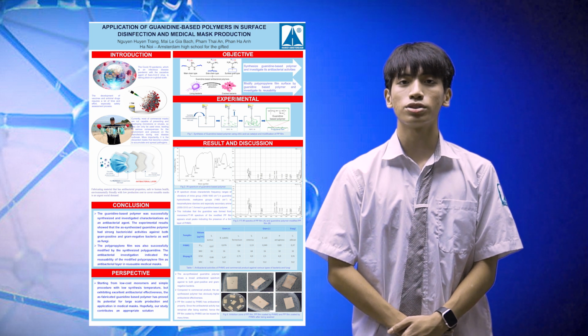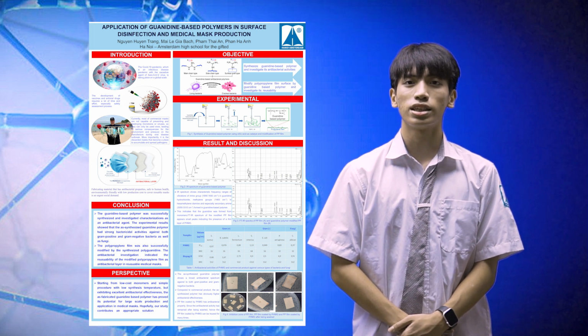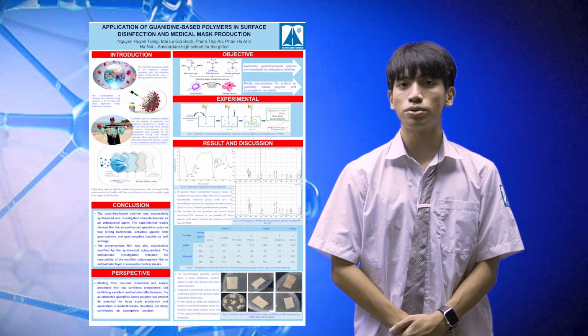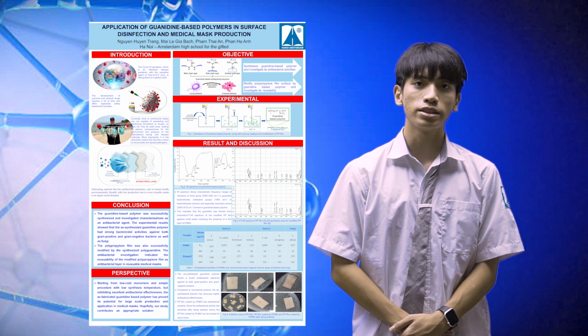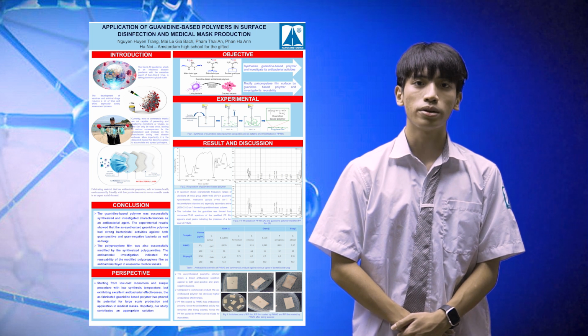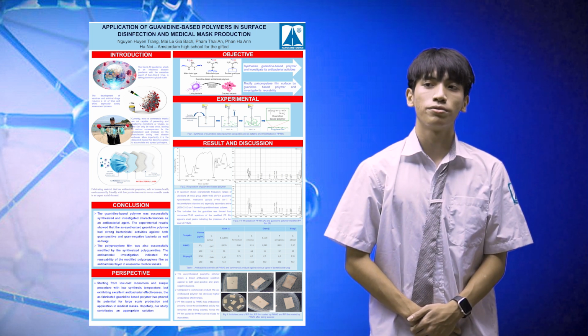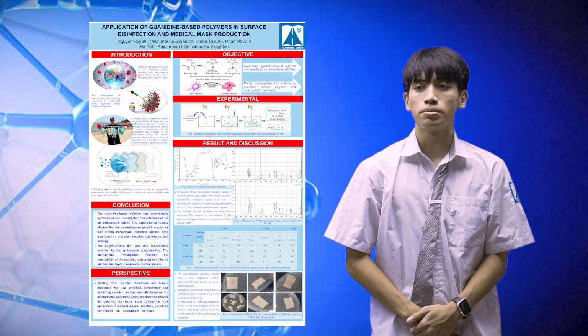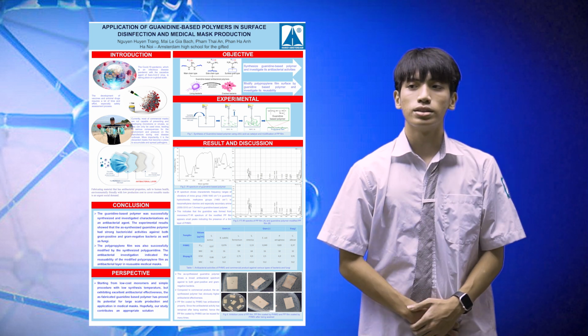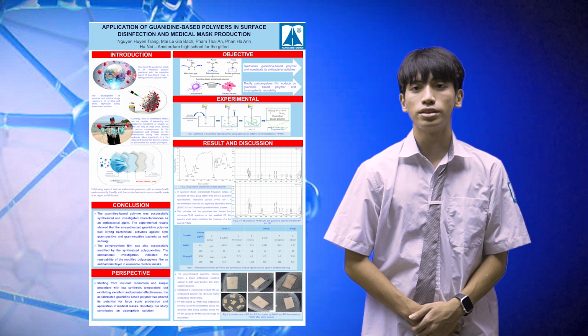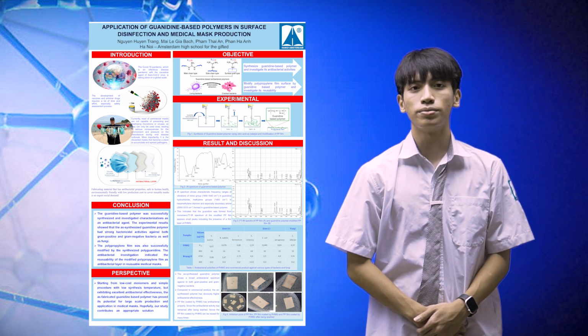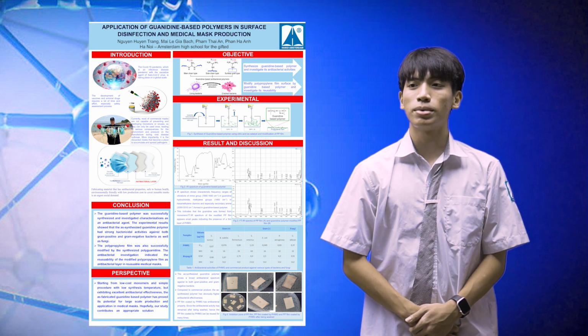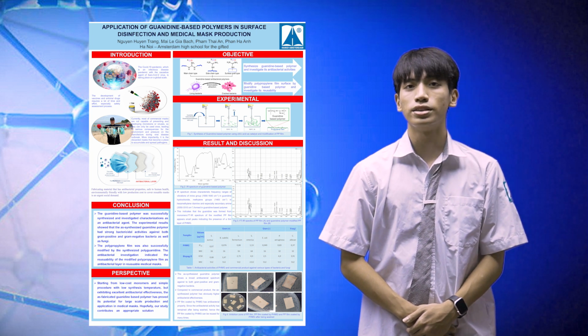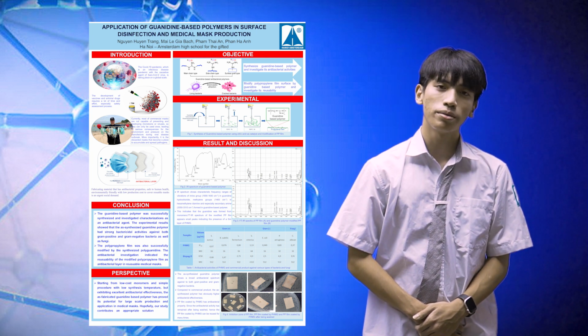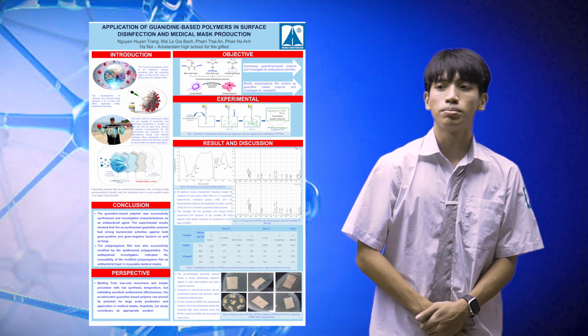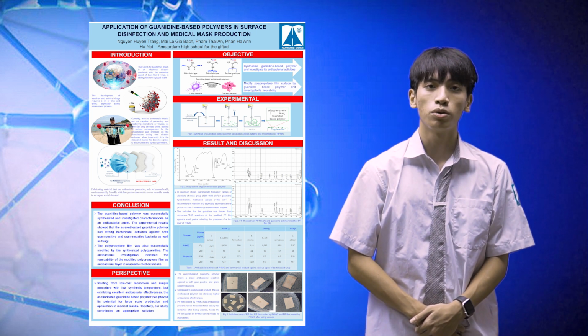To sum up, the guanidine-based polymer was successfully synthesized and characterized as an antibacterial agent. The experimental results show that the as-synthesized guanidine polymer has strong antibacterial activities against both gram-negative and gram-positive bacteria as well as fungi. The polypropylene film was also successfully modified by the synthesized polyguanidine. The antibacterial investigation indicated the reusability of the modified polypropylene film as antibacterial layers in reusable medical masks.